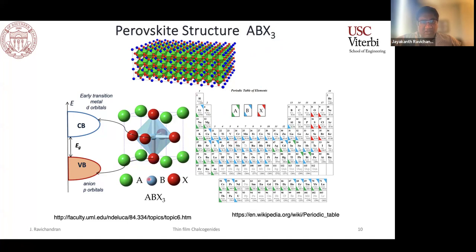For example, if you take this ABX3, the prototypical material you can think of on the chalcogenide side is barium zirconium sulfide, where barium goes into your A site, zirconium goes into your B site, and sulfur goes into your X site on your faces. And this leads to BX6 octahedra. And depending on what sort of composition you have, it will decide how your whole structure evolves here.